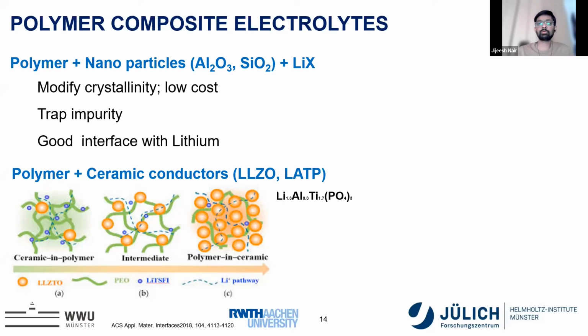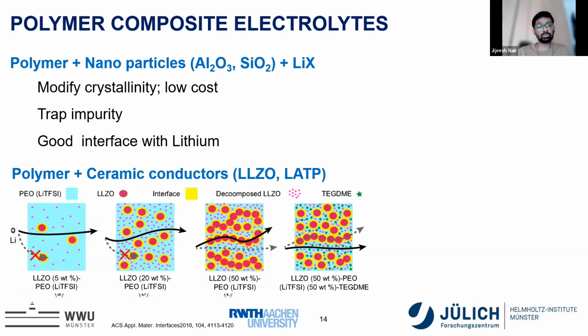But now, from the development of further technologies, we can produce small scale lithium ion conducting ceramic particles, which can also be used as a ceramic filler, which leads to a new kind of polymer electrolyte system called a hybrid electrolyte system, where the polymer can conduct along with the ceramic. Again, even in this case, you can produce ceramic in polymer, in which polymer is the major part and ceramics are a small part, or polymer in ceramic, where ceramic is the major part and polymer is the lesser part. According to that, you can even have a different conductivity. For example, in the case of LLZO-PEO, you have polymer that contributes mostly to the ionic conductivity, whereas in the case of LLZO in higher quantity, you have LLZO that contributes mostly to the ionic conduction.